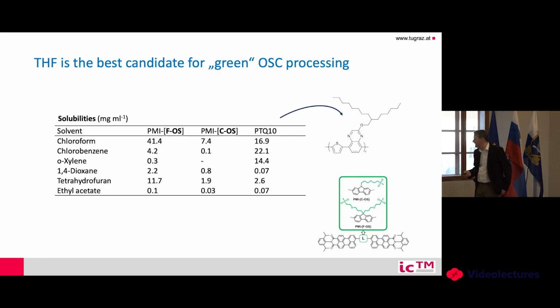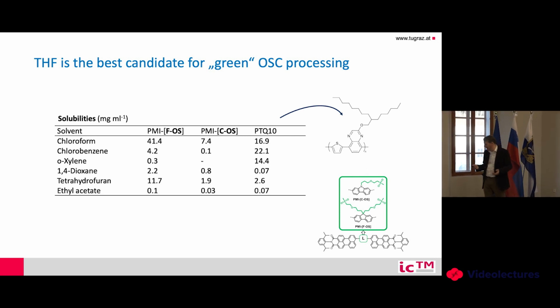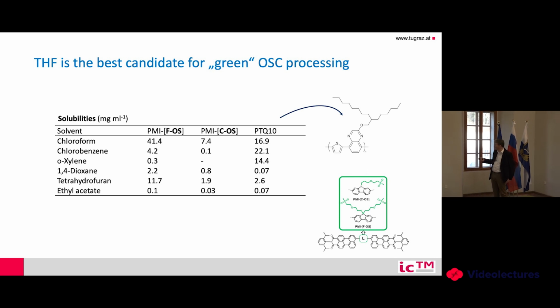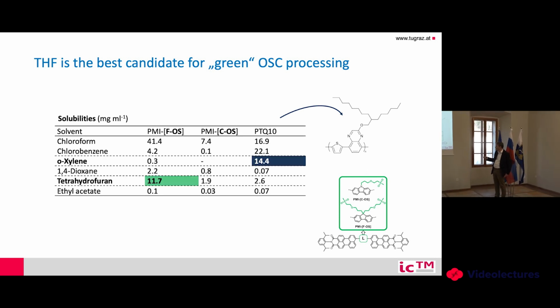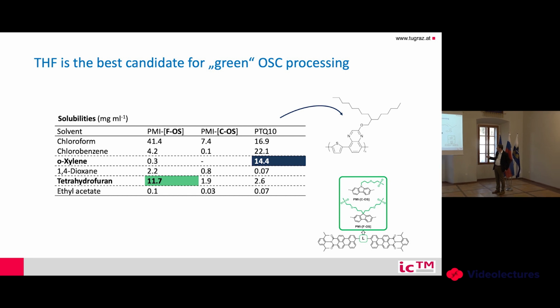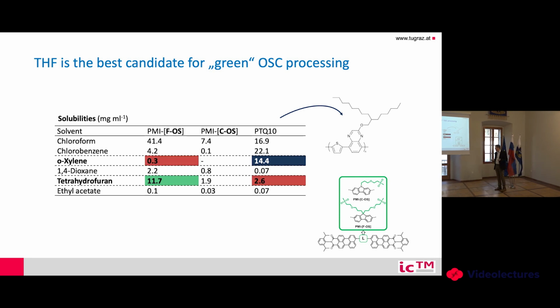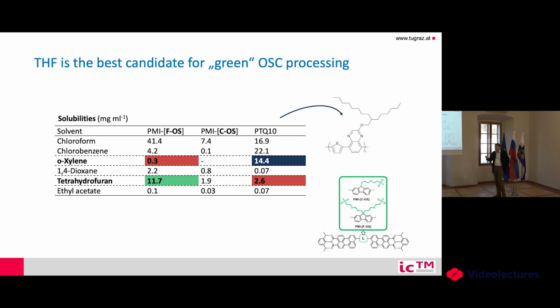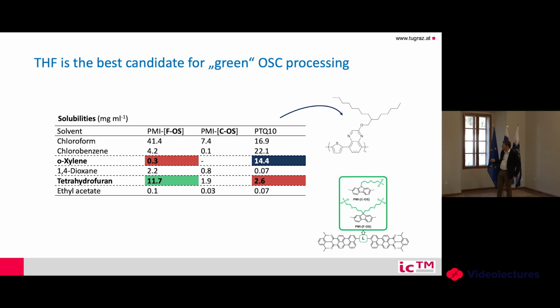However, then the trouble starts with making the solar cell, because we're making it from solution, so you have to find a good solvent. You have to look which solvent is working, and you see that we have no really good solvent where our new material, and the other material, are both really well soluble. Here you see a good solubility, but here it doesn't work. With chloroform you always have troubles, so we don't use it too often.